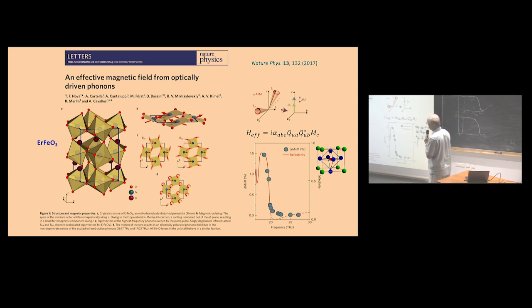This is a weak ferromagnet system, and they could measure this change of magnetization due to the magneto-optic Faraday effect or Kerr effect. And what happened here is that they excited two phonons. They had a polarization of pumping along the 110 direction, so they excited phonons along the A-axis and along the B-axis. And due to this simultaneous excitation, they practically produced movement of atoms along some direction, and this movement produces a magnetic moment. Again, this effect was explained by coupling of two phonons with magnetization.